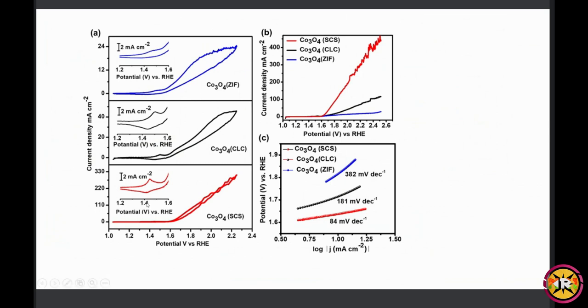And around 1.4 volt, there is an intense peak, which is the formation of Co4+ from Co3+. When I have done these reactions in KOH medium in presence of electrolyte, as I have told, in Co3O4, Co2+ and Co3+ are present there, but in presence of these reaction conditions, some Co3+ is converted to Co4+. What I have shown in the inset, this around 1.4 volt.